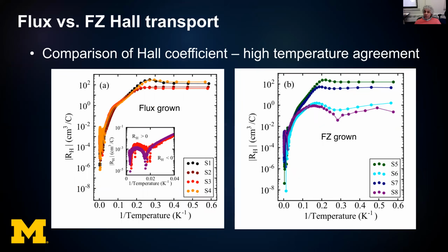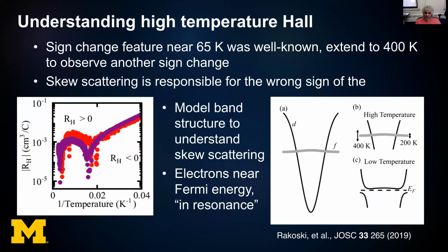When you look at the Hall effect, and again, with Hall measurements we're going to be focusing on high temperatures, we see a well-known reversal of the Hall coefficient at high temperature. Instead of getting a negative Hall coefficient indicating electrons, we get a positive coefficient, which is due to the skew scattering. And when we compare the samples at high temperatures, we don't see dramatic differences, except these 2 samples at low temperatures again have different Hall coefficients.